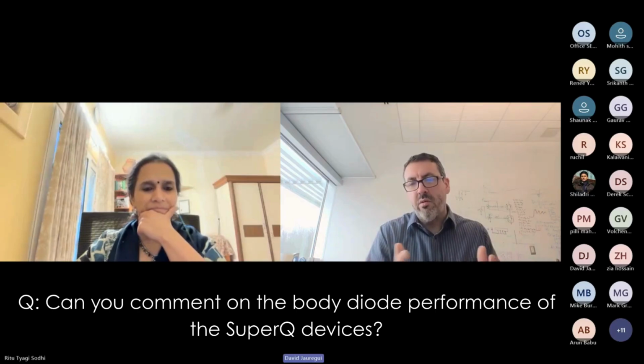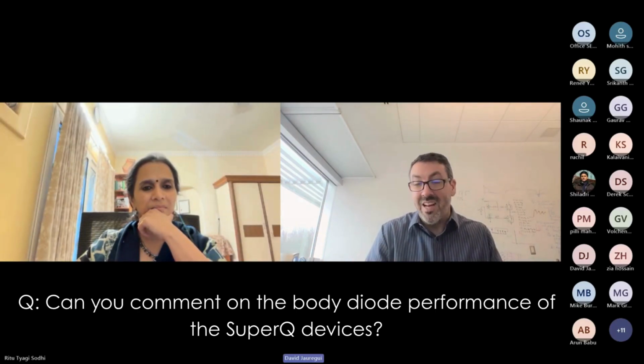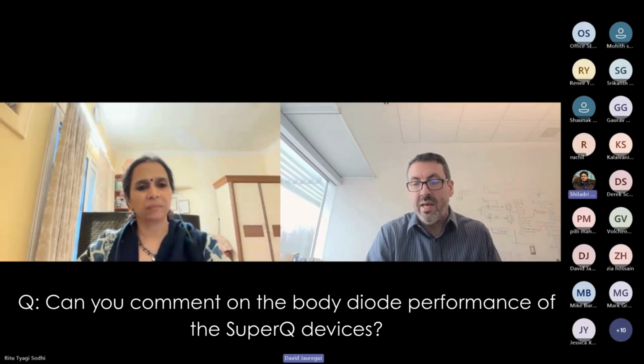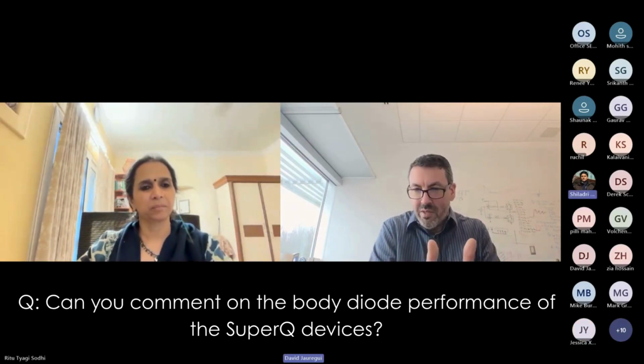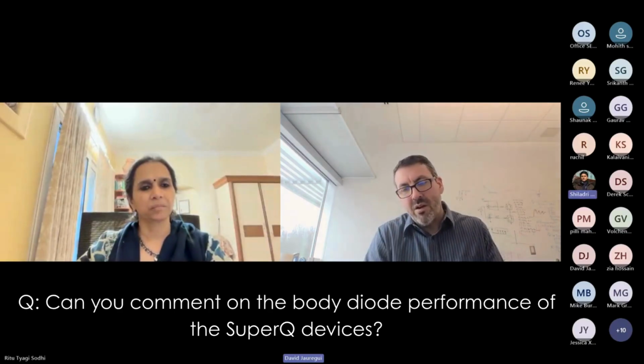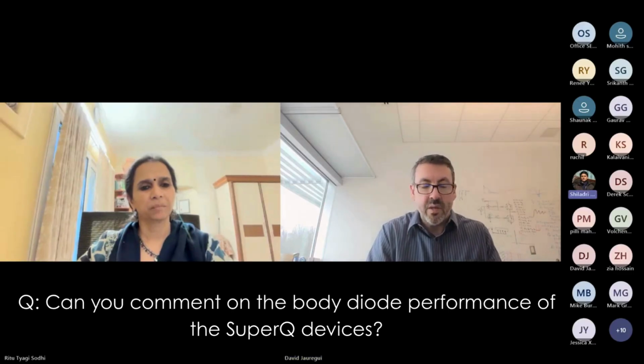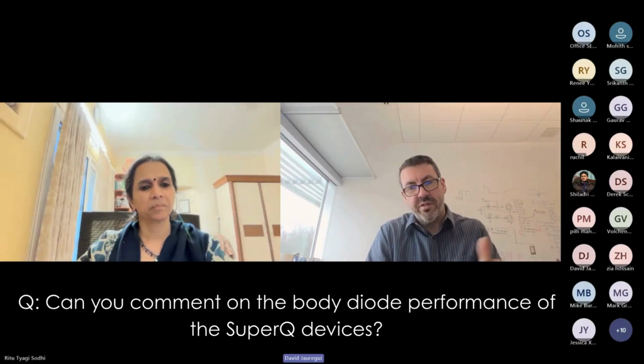The industry wants narrower dead times because of losses. Why? Because GaN does not have a body diode. It has an I times V product, and that in itself is a loss parameter that needs to be managed by narrowing the dead time. Same with silicon carbide. The VF drop is so high that the loss becomes prohibitive. And so once you get to 100 nanoseconds or less, and particularly for 600-volt MOSFETs, the impact of reverse recovery becomes a lot less. Actually, it's almost negligible when it comes to loss.